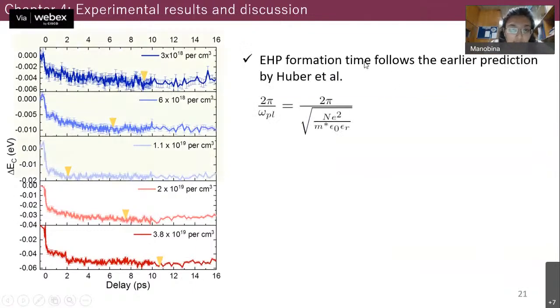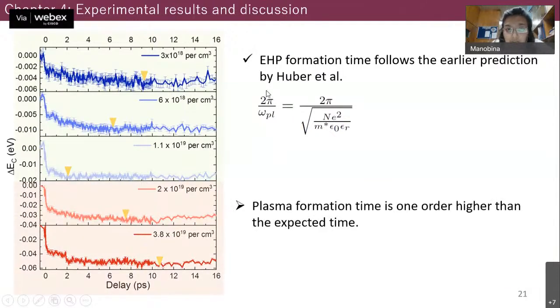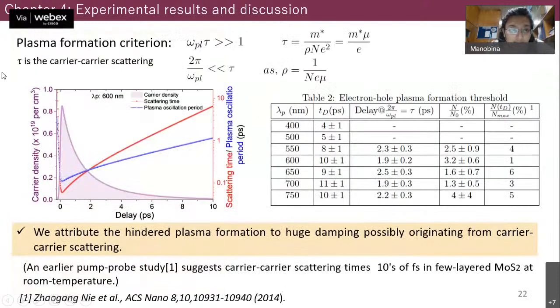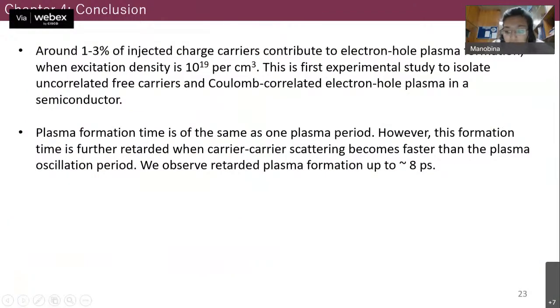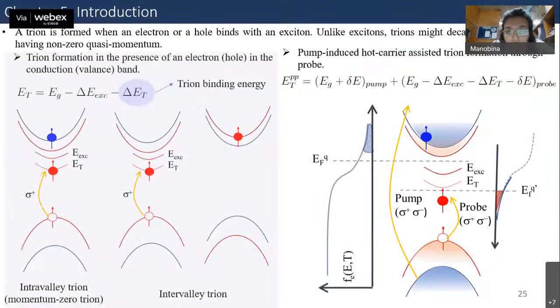Next, we vary the carrier density and observe that the plasma formation time first reduces and then again increases. So at certain level, it follows whatever Huber had predicted, but after a certain threshold, it does not follow because here this carrier scattering time becomes very fast. So these are the main conclusions from this chapter. Now I'll just briefly move over to this.